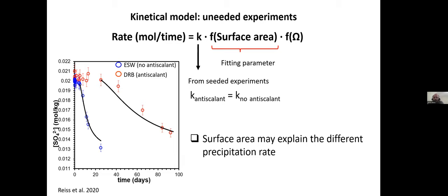This time the surface area was a free parameter, and you could see the nice fit of the model to the experimental results. So this basically tells me that the surface area that's created during nucleation is what determines the overall precipitation rate of gypsum in these conditions.